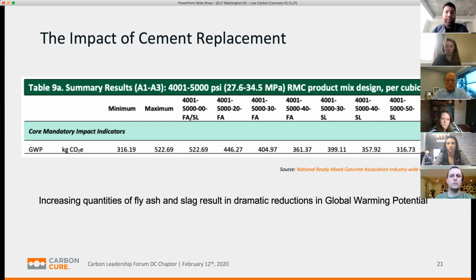But then the key thing about this I wanted to show you as well is that if you look at the top here, the labeling is kind of hard to read, so I'll explain this for you. There's one that says 4001-5000-00, FASL. In this case, FA means fly ash, and SL just means steel slag. So those are cement replacements that Teck will speak to. But what that's showing you is that that is a standard mix that only uses cement. And what it's saying there is that that mix should be somewhere in the order of 522 kilograms of CO2 per cubic meter of concrete.